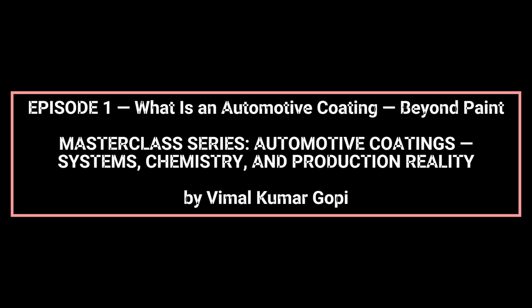Automotive coatings are approved and validated as complete systems, not as individual layers. Solvent interaction between layers affects intercoat adhesion. Rheology in one layer influences how the next layer wets, flows, and bonds. Cure schedules are optimized for the full stack, not a single film. A change in base coat solvent balance, for example, can impact clear coat flow or primer adhesion, even if the base coat itself appears acceptable in isolation. This is why OEMs approve coating systems rather than standalone products. System-level validation ensures corrosion resistance, appearance consistency, and durability across millions of vehicles under real-world conditions.